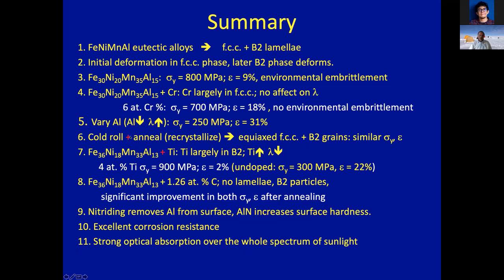We looked at cold rolling these materials and annealing them to recrystallize, and we ended up with an equiaxed FCC plus B2 grain structure, which had a very similar yield strength and elongation to failure to the material we started out with. We looked at adding titanium to this material, and titanium increased the yield strength, compared to the material that had a yield strength of about 300 MPa. So it tremendously increased the yield strength, but unfortunately the ductility dropped really dramatically. And again, this is because the lamellar spacing decreased quite dramatically.